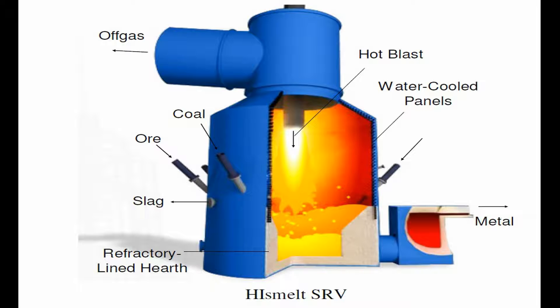The process uses high-velocity injection of coal and ore into the melt via downwardly angled water-cooled injection lances. Injected coal, after heating and devolatilization, dissolves to maintain around 4% carbon in the metal. Injected ore is then brought into contact with this carbon-rich metal, and smelting occurs. The lower part of the SRV is maintained at low oxygen potential to allow this reaction to occur.